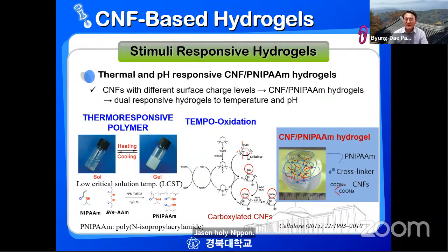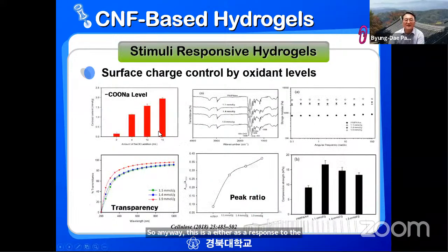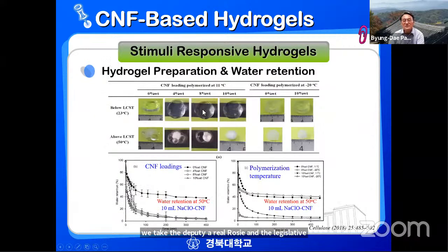So anyway, this is a hydrogel responsive to the temperature and also pHs. And then we use different amount of the oxidant levels to have different charge levels. And then we check the FTIR, rheology, and the compression strength, those kind of things. And then we also use the different amount of nanocellulose in the composition in the polymer. And also we have different LCST and also polymerized, which this is the radical polymerization, right?